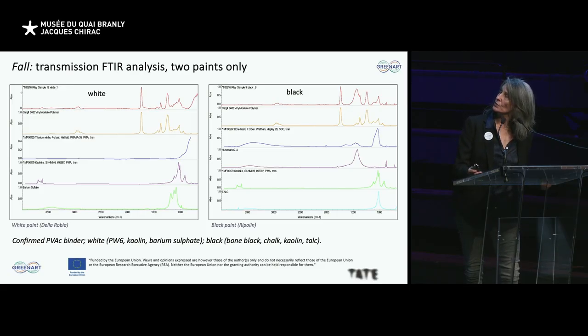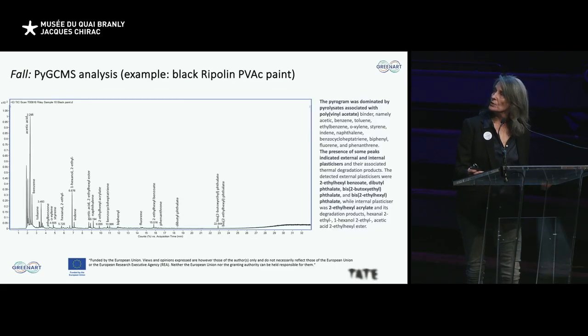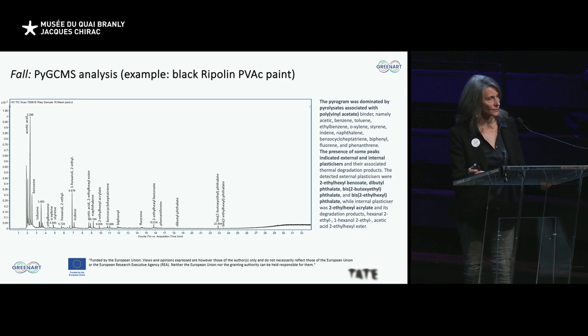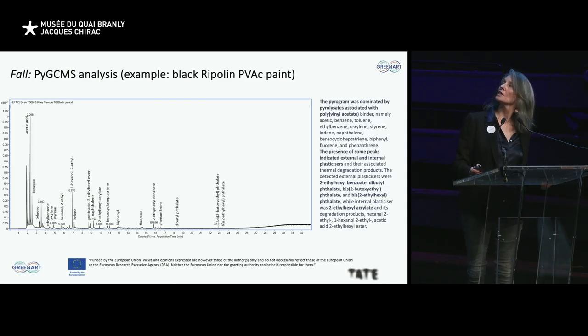Because the Ripolin research so far is focused on the earlier resinous paints available to artists. So the black paint is bone black, chalk, kaolin, and talc, and there's also some iron oxide black in there as well. So relatively simple constructions. Pyrolysis GCMS, of course, far from simple if anyone's used it, but this definitely confirms polyvinyl acetate, and also we were quite interested in the plasticizers and other additives in these paints. Because they haven't been looked at hugely in the conservation field in terms of conservation treatment risk.